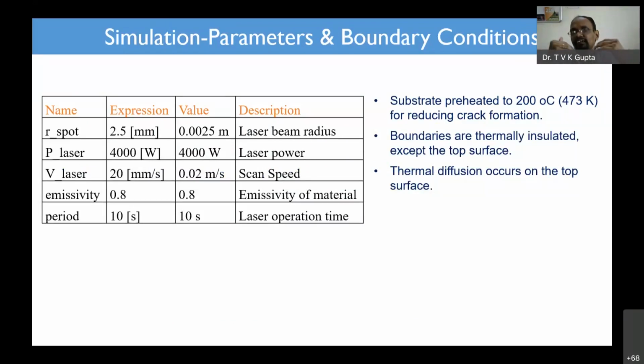You have to make the entire thing in a single form, because the distortion is happening because of the temperature. When you say distortion because of the temperature, that means you are going to have a heat transfer module. But the distortion is a mechanical phenomenon, so you will be having a von Mises criterion. So you have to couple both this mechanical module and the heat transfer module in order to get the distortion. Also, the residual stresses can be calculated from the software. And the same thing you can always do in experiments also.